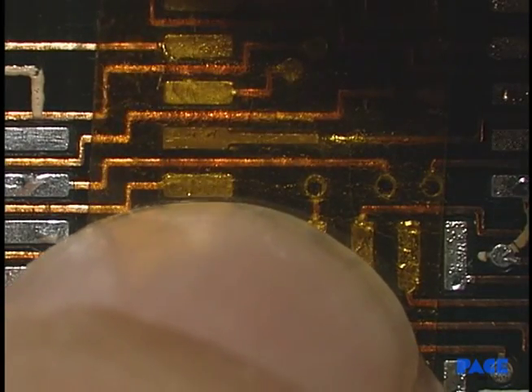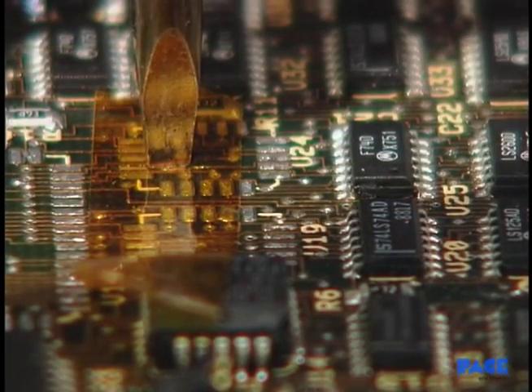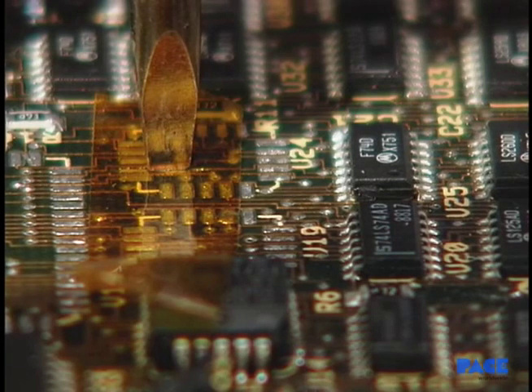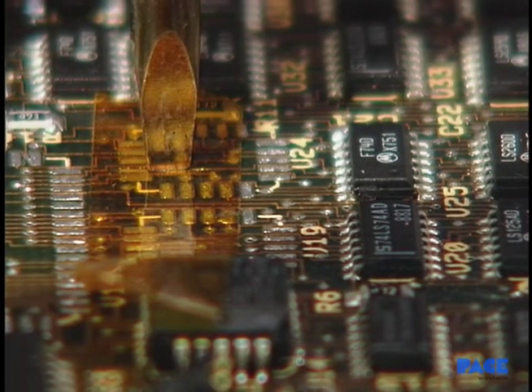When the new circuitry is placed, the convenient thermosetting adhesive is hot bonded in only 15 seconds at a safe low temperature of 315 degrees Celsius. Thermobon technology saves repair time, requires no messy mixing of liquid epoxies, and restores the circuit board to its original reliability.